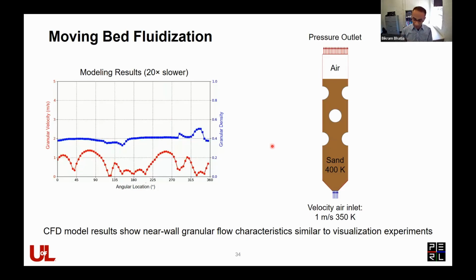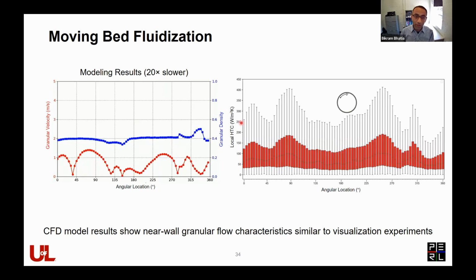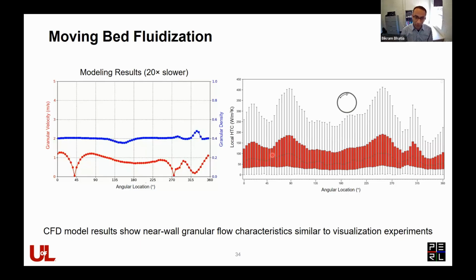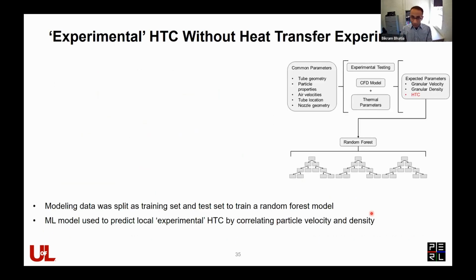So we use this model, including the energy equation, to predict what the local heat transfer coefficient is. So that's heat transfer from the hot sand to the tube wall as a function of angular location. And we sort of average it over time. And that's what you're seeing here. So the horizontal narrow bars represent the mean. The red bars represent one standard deviation, and the total range of the measurements that we got from this model are represented by these large vertical bars.